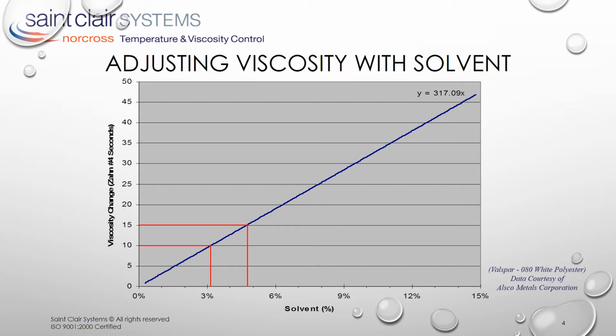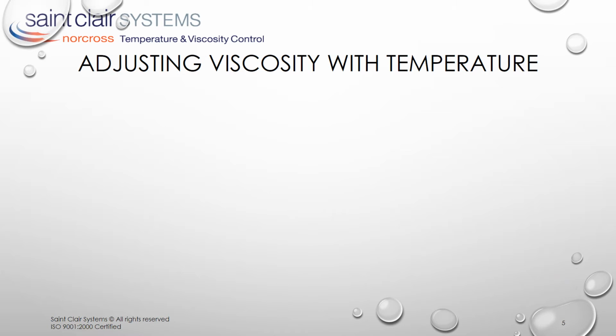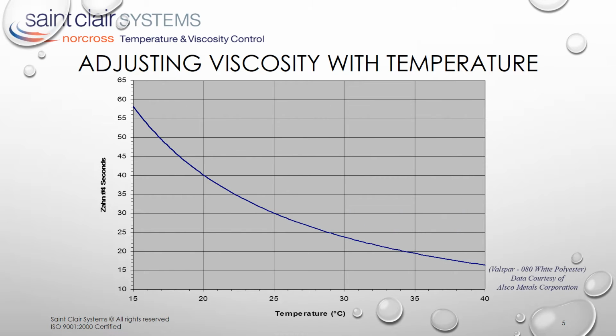To make matters worse, too much solvent can cause issues such as blister, pop, orange peel, low gloss, and even off-color defects. These factors combine to make minimizing solvent addition a worthwhile objective. To correlate temperature to solvent addition, we return to the viscosity versus temperature graph.